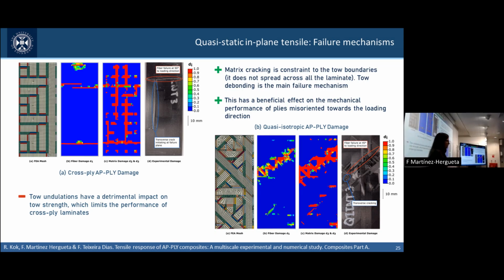So we use these models to give some understanding of the response of the laminates. It is evident that the cross-ply laminate failed due to fiber failure. We can predict the kink cracks that occur through the undulations. But it's also interesting to appreciate the pattern of matrix cracking over both laminates. In a conventional cross-ply laminate or a conventional quasi-isotropic laminate, we will find that matrix cracking is spread all over the laminate. In this case, all matrix cracking is within the tow boundaries. That means that the undulations are acting as crack arrestors.